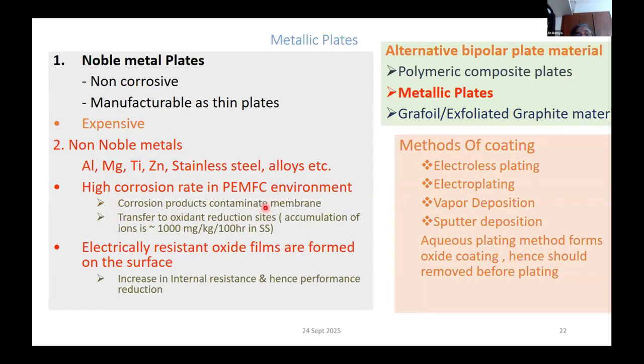If you do a noble metal based plate, then it is non-corrosive and very good to manufacture. You can do thin plates, but they are very, very expensive. So what you do is go for a non-noble metal like aluminum, magnesium, titanium, or stainless steel or alloys, and then try to do a high corrosion resistant coating on them. Otherwise, the metals that are leached out will contaminate your membrane. So you have to do a corrosion protection coating. Basically, it can be done by various techniques like electroless plating, electroplating, vapor deposition, and so on.